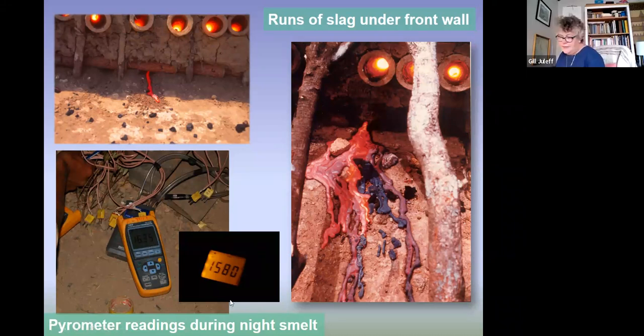On a number of the smelts, we are able to use pyrometers to record temperatures we are reaching. And right in the combustion zones, we are reaching some phenomenal temperatures, over 1400 degrees centigrade. And in one case, we went over 1500 degrees centigrade. So without having to pump a bellows or do anything, this furnace of its own accord will run at very high temperatures.